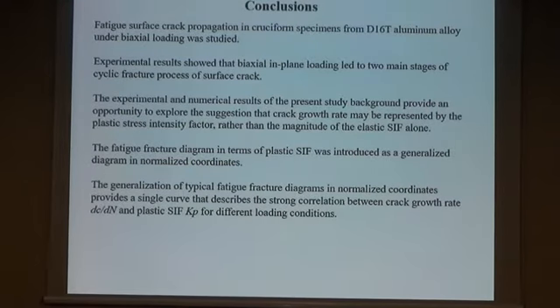The fatigue fracture diagrams in terms of plastic stress intensity factors were introduced as a generalized diagram in normalized coordinates. And generalization of typical crack growth rate diagrams in normalized coordinates provides a single curve that describes a strong correlation between crack growth rate and the plastic stress intensity factor for different loading conditions.